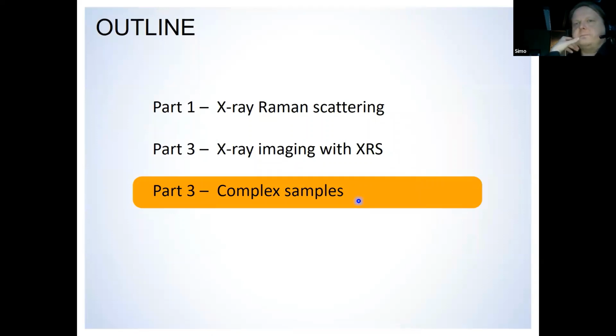So, questions at this point? Yeah, Simo, thanks. That's great. What kind of spatial resolution can you get with this method, and what do you think is the limiting factor? At the moment, the limiting factor is basically the detector pixel size, because we need a photon counting detector. These are typically in the range of, for example, the Medipix family, which has a 55 micrometer pixel size. So with a 1-to-1 focusing geometry, the limit is basically that. And then if the pixel size of the detectors could be improved, the limiting part will be the crystal optics, how perfect this spherically bent crystal analyzer can be made. We are not there yet, because the detector is at the moment the limiting factor.